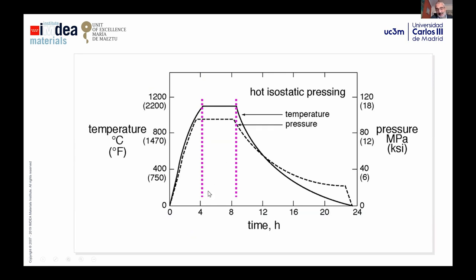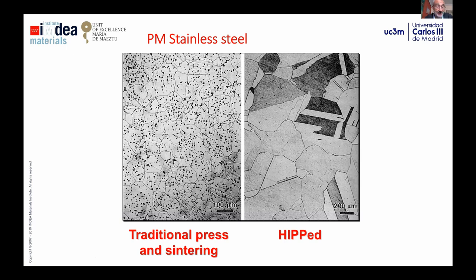Sometimes the dwell time needed to reach these properties is in the order of hours, 2, 3, 4 hours. That means it's a long process that usually makes it quite expensive. And in terms of the microstructure, one of the problems of hot isostatic pressing, if you need such long times to reach the correct microstructure, is shown on the left: a traditional press and sinter stainless steel, in which you see the microstructure with a lot of porosity. After HIPping, you get a fully dense material without any porosity.